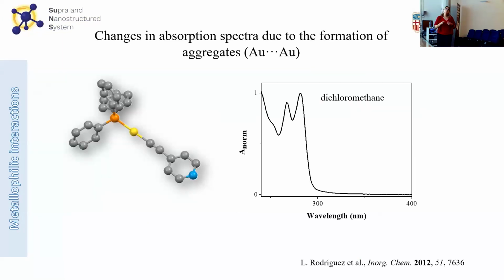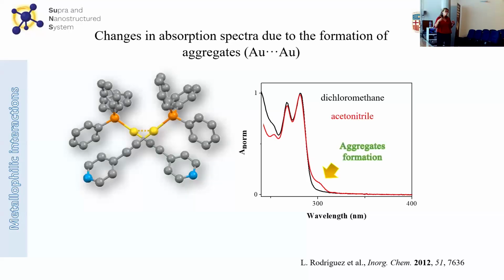Is it a requirement to have a dinuclear compound to see these aurophilic interactions? Well, the answer is no. We can also have a mononuclear compound, but the presence of intermolecular aurophilic contacts can be favored if we put the molecule in a solvent that tends to make it aggregate a little bit. This is the case of this molecule: in dichloromethane it gave the absorption spectrum that I previously showed, but if the molecule is in acetonitrile, it tends to aggregate since it is not so comfortable. The molecule is hydrophobic, and acetonitrile is more polar. In these cases, it tends to aggregate, giving rise to the formation of these aurophilic contacts.